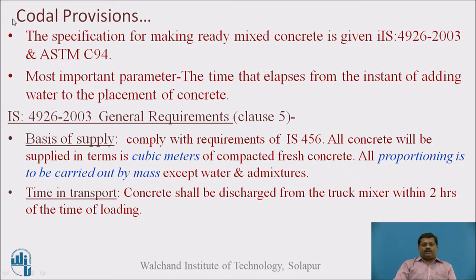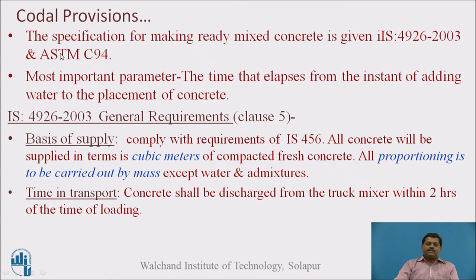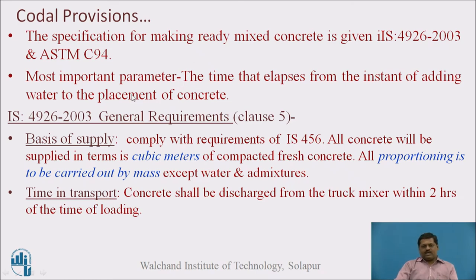These are the codal provisions. For making ready-mix concrete, we have IS 4926-2003 and the American Society for Testing and Materials code ASTM C-94. The most important parameter in both codes is the time that elapses from the instant of adding water to the placement of concrete.